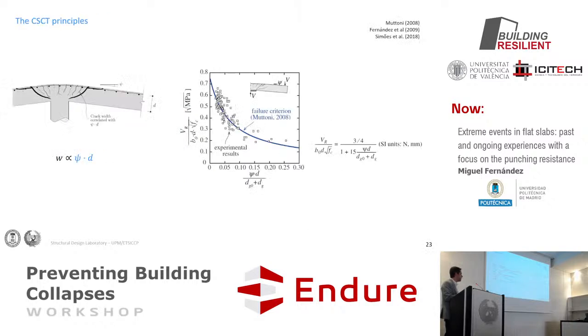There are also other considerations, but I will not go very much in detail, sorry, I don't have too much time. As this parameter is depending on something I think is very interesting, it depends on the rotation, so on a strain parameter, and it depends also on a size parameter. So the actual key parameter depends on the strain and the size. By increasing the strain, you have this strain effect. By increasing the size, you also get a size effect. So more strain or more size decreases your strength.